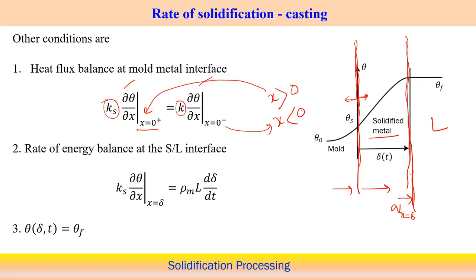Then at this point, x equal to delta T, the heat flux, which indicates Q at delta T, should be equal to the heat released to solidify, changing the liquid phase to solid phase. Therefore, rho m into L, the latent heat, into d delta by dt. This is the velocity of the solidification front moving along the x direction. So, this is another boundary condition, and the third boundary condition is